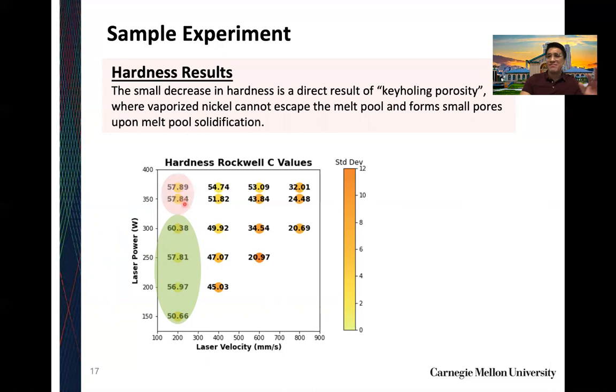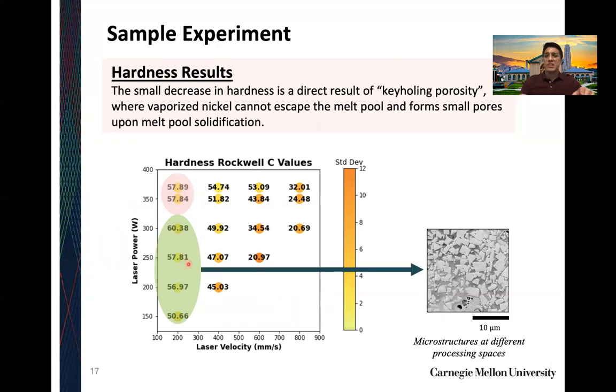but there is a slight noticeable drop off here, and I was very curious as to why that was. Why are we getting lower hardness values at a higher power, which goes against the previous trend I mentioned? Well, if we look at the SEM microstructure, for all our samples we had a very homogeneous distribution of tungsten carbide nickel. We didn't get any pockets of agglomerated tungsten carbide, which is very good for us because you always want a homogeneously distributed particle in your metal matrix composite.